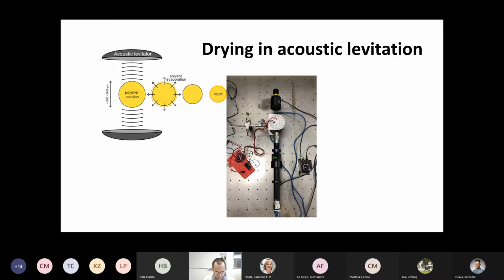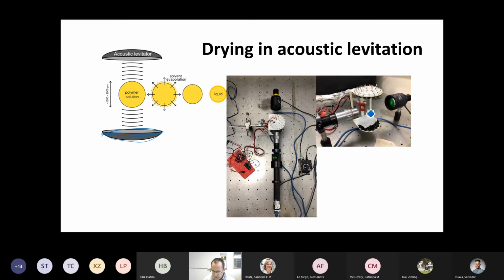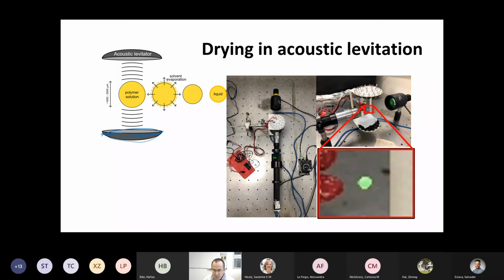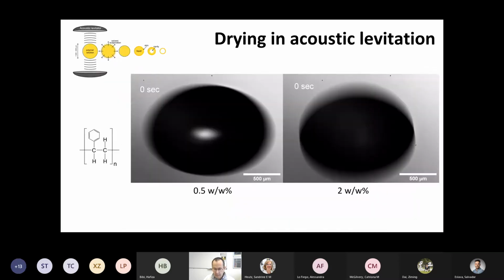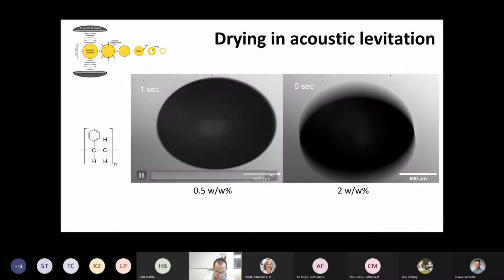You create some kind of dome packed with tiny loudspeakers that will apply a force that is opposed to the gravitational force. And you suspend particles very readily, and you can follow them optically, for example, but also with scattering techniques, which is what we use. And here's a particle. Typically, these are formed within a couple of hundreds of microns to millimeter scale, for example. And very quickly, you realize that interesting things happen too.